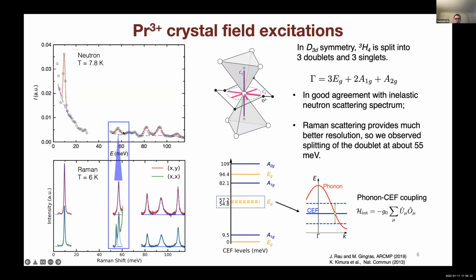Now here I present a comparison of the neutron spectrum and the Raman spectrum. In general, they are in great agreement, and both methods observe the transitions from the ground state to all of the excited states. But with better resolution, we noticed that the doublet around 55 meV is split in the Raman spectrum, and the 2 components of the doublet can be well separated by polarizations.